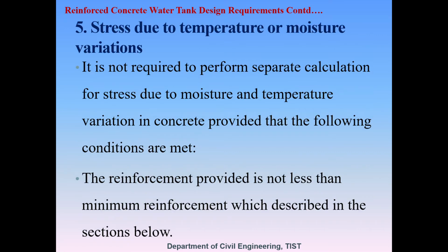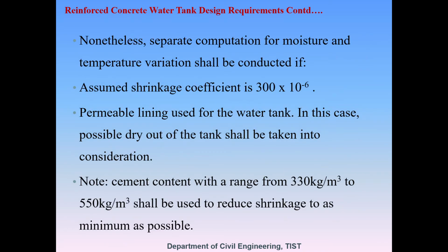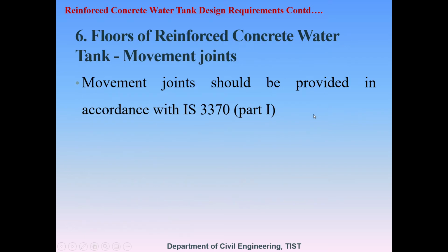The fifth requirement is stress due to temperature or moisture variations. It is not required to perform separate calculation for stress due to moisture and temperature variation in concrete, provided that the following conditions are met. Separate computation for moisture and temperature variation shall be conducted if assumed shrinkage coefficient is 300 into 10 raised to minus 6 and permeable lining is used for the water tank, etc.